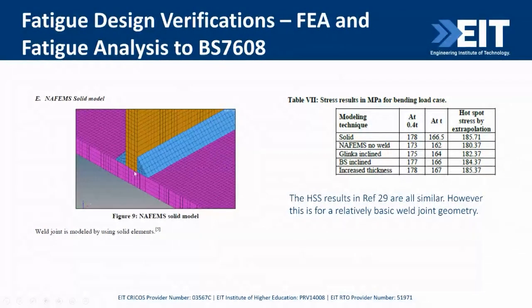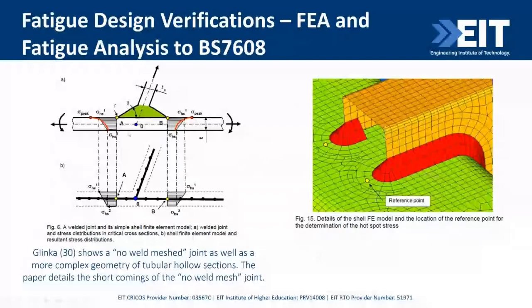Obviously solids, but you'll have your gap here to account for the root and the fact that you haven't got full penetration weld. If you've got a full penetration weld, obviously mesh that. But for a T-butt fillet weld, that's got to be meshed. So reference 29 went and worked out the hotspot stress results for 2 load cases. And the results are similar, but that's only for two simple geometries, and Glinka has outlined it better here.